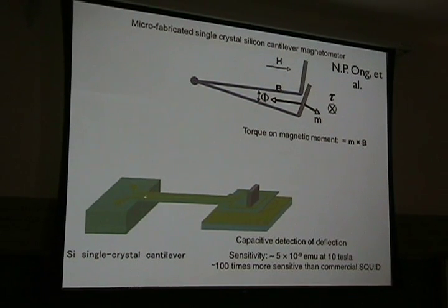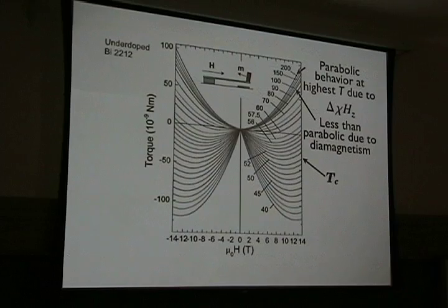So this is the arrangement. It's a very thin silicon cantilever, and here's a capacitor to measure the deflection. And it's very sensitive, 5 × 10⁻⁹ EMU at 10 Tesla. Okay, so this is the result, and it's really amazing because at high temperatures in the normal state, you see it's just